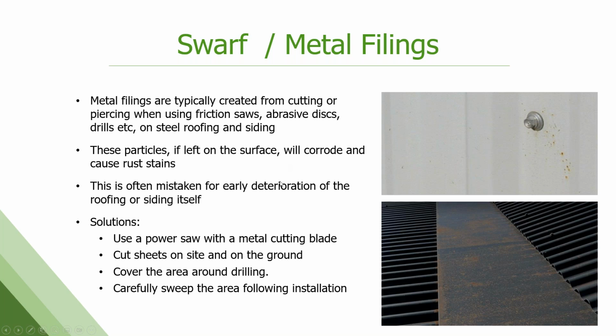Swarf and metal filings. Swarf is the little debris particles left from cutting, drilling, and sawing that has to occur on a job site. That gets deposited on the surface. If you don't clean them off, then they start to rust. This comes to me as a rust claim on the panels. It's not; it's these little pieces of metal on the surface that have now rusted away, and they've left a red or brown stain on the painted surface. Probably not going to cause the paint to fail, but it doesn't look good. No one's happy with it. It's an installation issue, a contractor issue. And we do have a lot of bulletins and guidelines on how to properly cut, saw, drill, and clean up so that this doesn't happen.